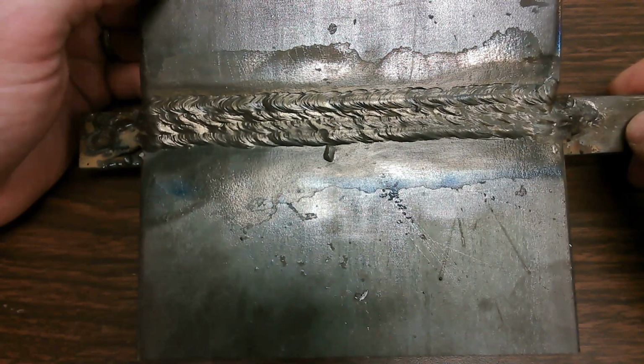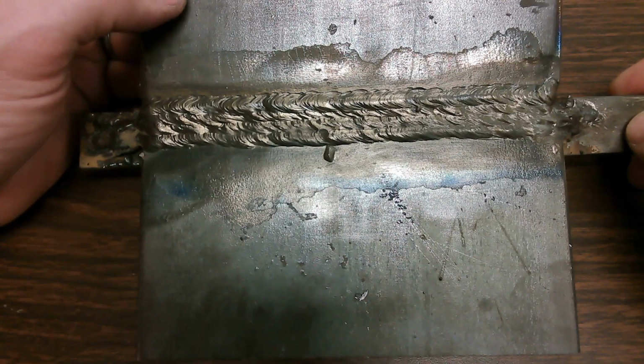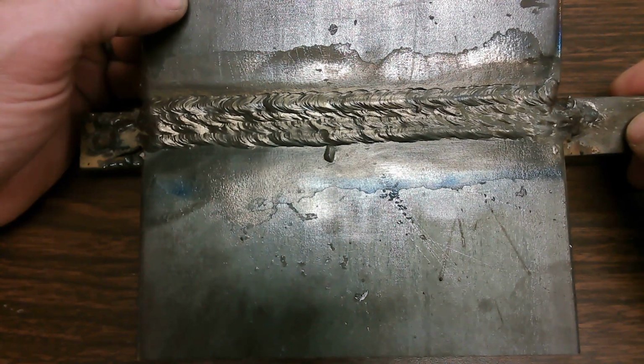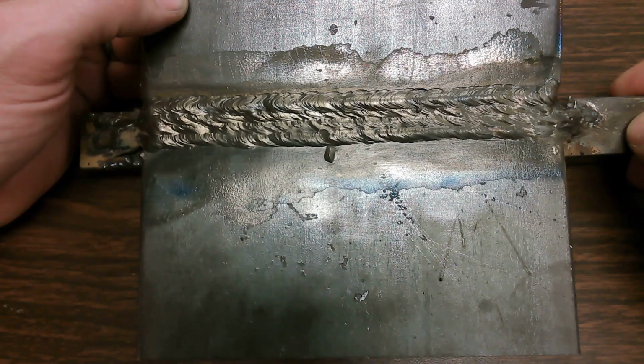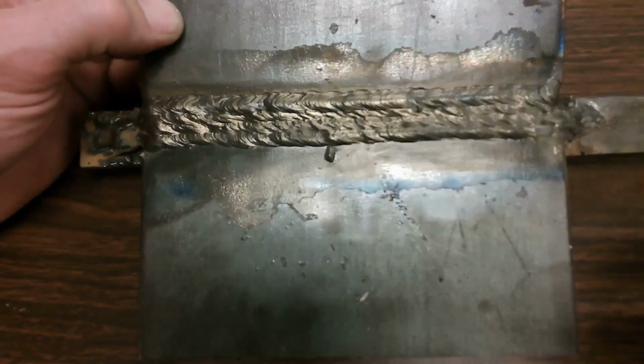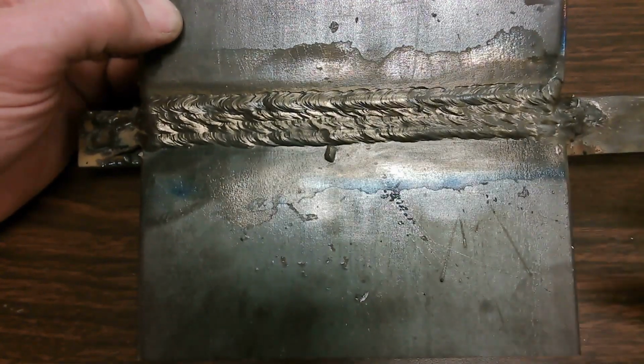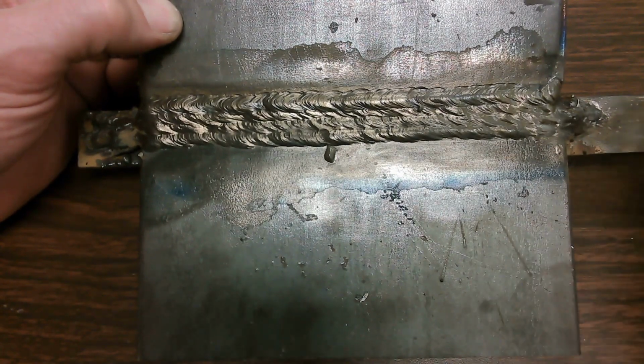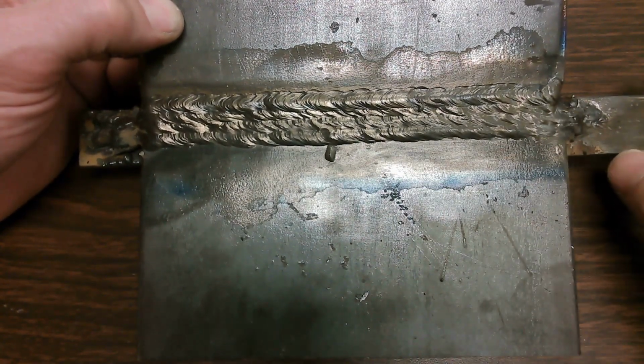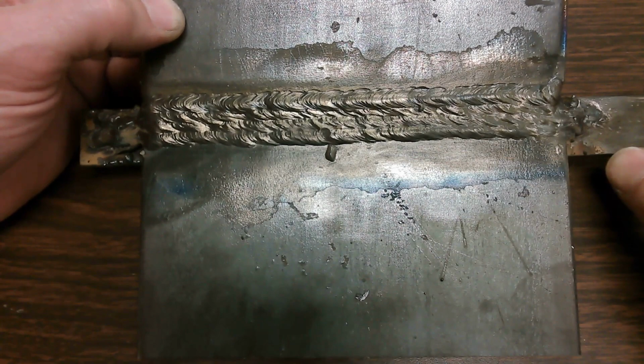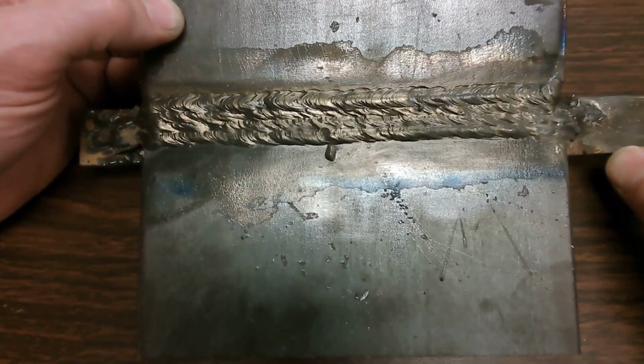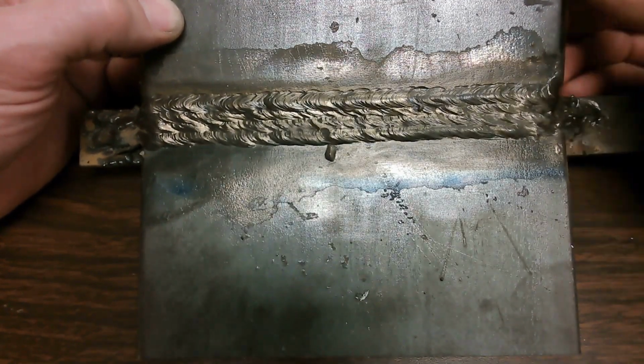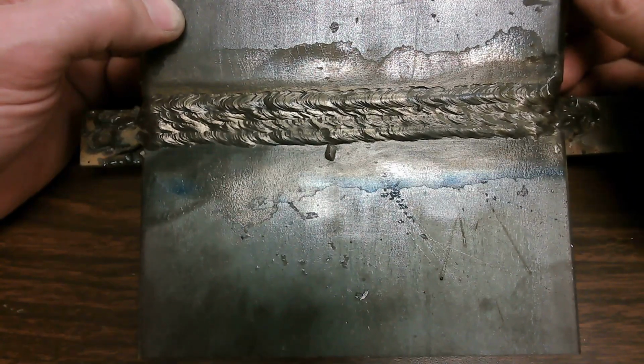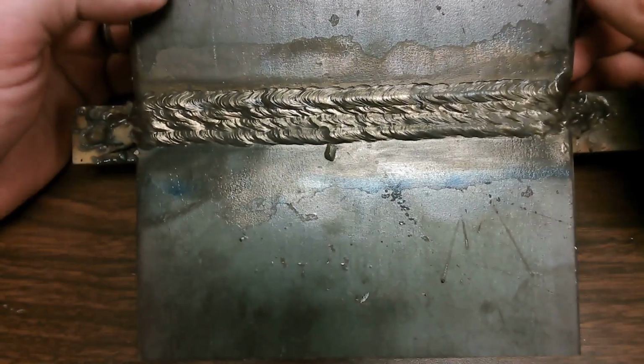What happens is you have a localized heat affected zone. It heats up very quickly and then subsequently cools that metal incredibly fast, because the thickness of the plate just absorbs that heat so fast because it's such a small area. You get a really quick, rapid cooling in that spot. And that, on a structural member, could be a critical thing that creates a stress spot in that metal. So that's why they don't want to see arc strikes. We want to look for those.